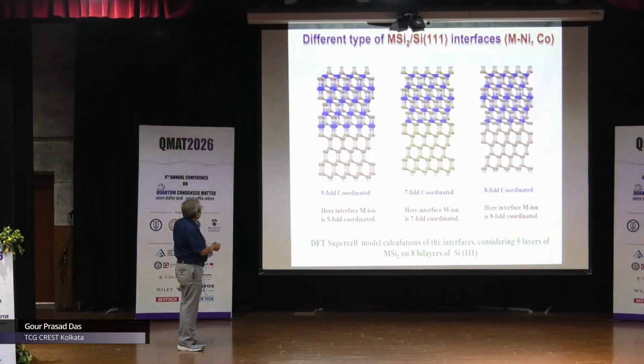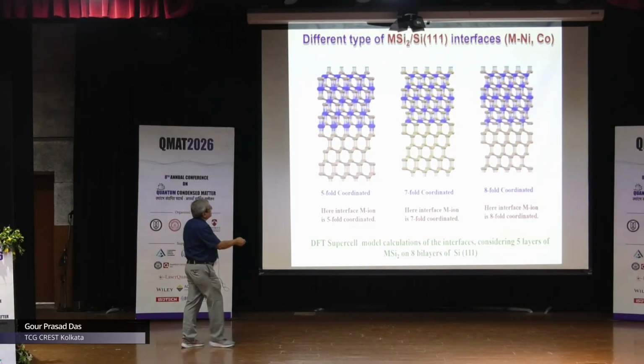is the coordination at the interface. How is the nickel, the nickel of the nickel disilicide, that is the metal, how is that coordinated with that of the silicon? This is silicon 111 and this is nickel disilicide. This is called 5-fold coordinated. This is 7-fold coordinated. That is very simple.